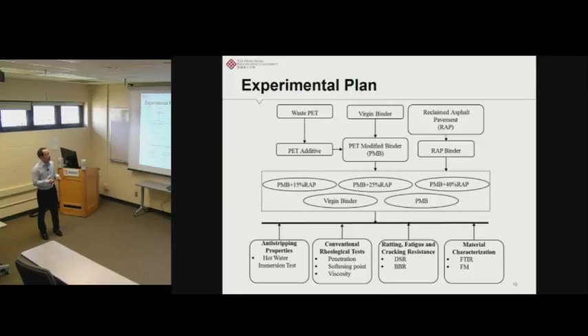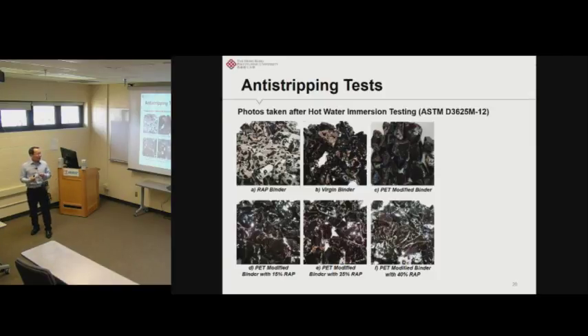And also we collected the field RAP samples, and then we did the extraction to get the RAP binder. And then we did artificial blending of the PET modified binder with different percentages of the RAP binder. So here RAP represents the RAP binder. And also we have the virgin binder and the PET modified binder without any RAP binder as control materials. So in total 5 binders. And for each binder, we conducted the anti-stripping property test, the conventional penetration, softening point, and viscosity tests, and also the DSR and BBR tests. And finally, we did some material characterization analysis. Now I'm just going to quickly go through the results we have obtained for each of the tests.